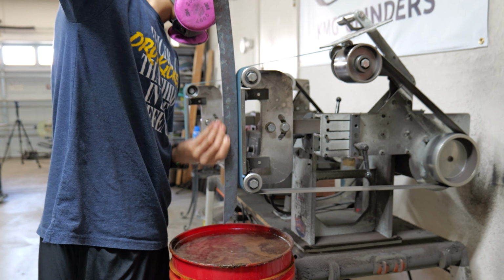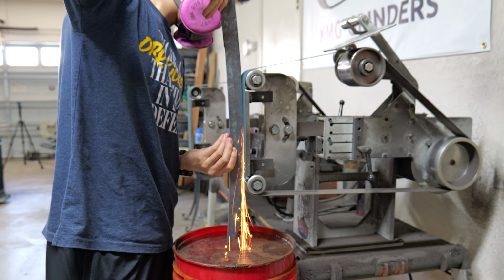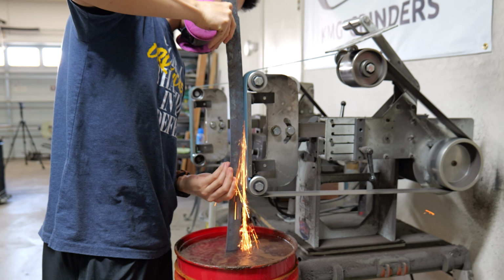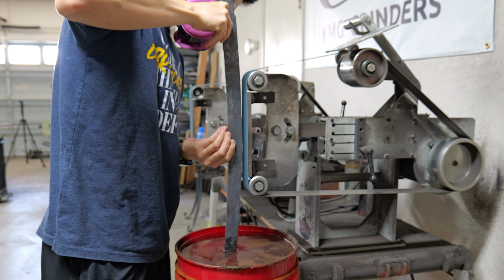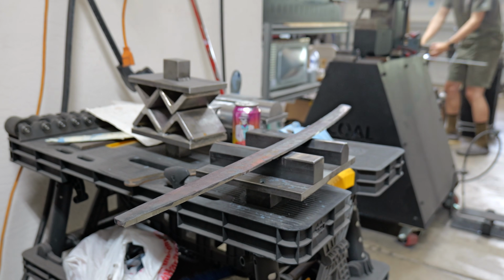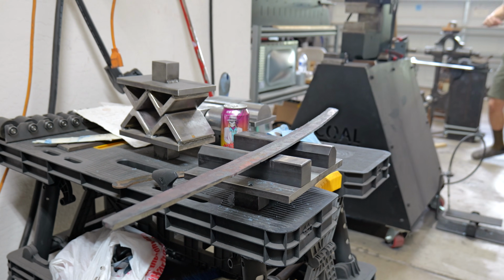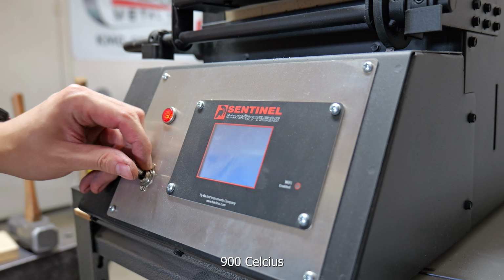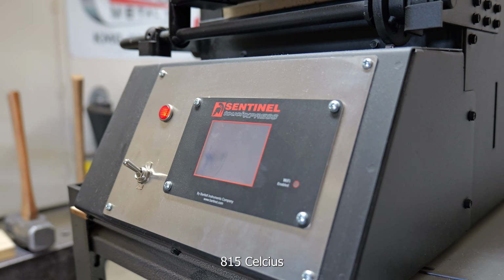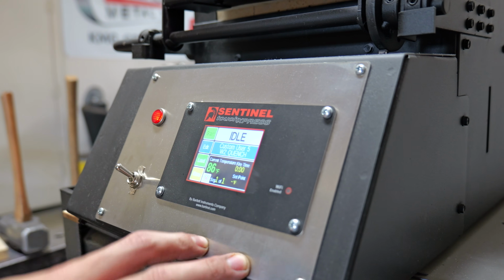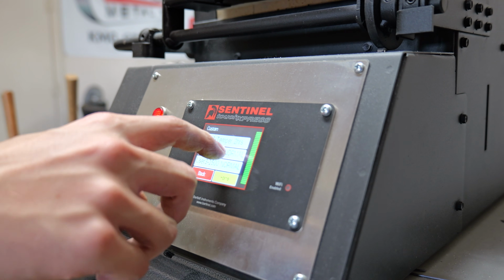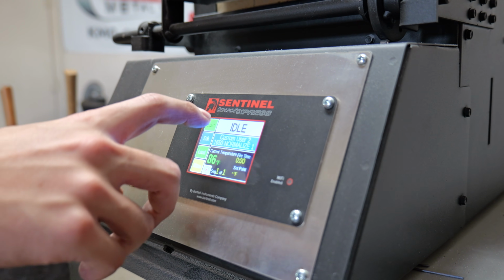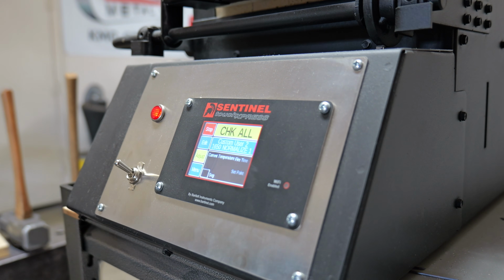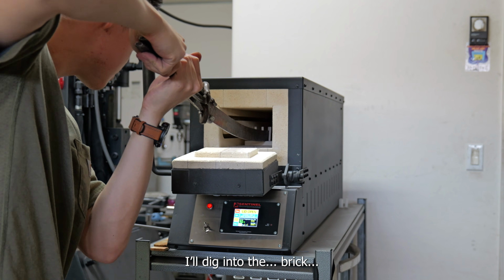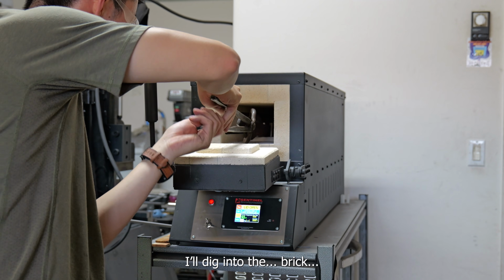Now that the blade is finished forged, it's time to get it ready for normalization. Normalization makes it so that the grain size gets smaller and that it heat treats perfectly. I do it in 3 cycles, the first one at 1650 degrees, the second at 1500 degrees, and the third one is at 1350 degrees. In between all 3 cycles, I let it cool to around 700 to 800 degrees. Edge side down, or else I'll just dig into it.